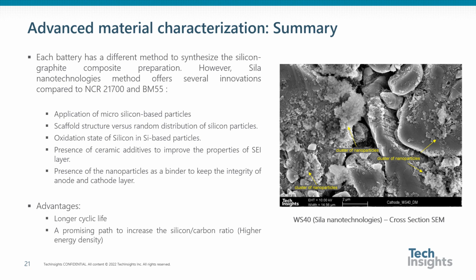A different oxidation state of the silicon in the silicon-based particles. In WS40, the oxidation state of the silicon is different from the NCR21700 and BM55, but still, it's not pure silicon. The presence of a ceramic additive to improve the properties of the SEI layer. Also, the presence of nanoparticles as a binder to keep the integrity of the anode and cathode layers. These nanoparticles are shown in this figure.